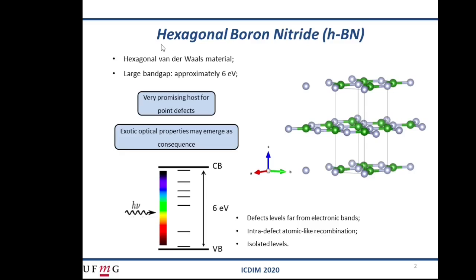Well, here we have a brief overview about some properties of hexagonal boron nitride. This material is formed stacking these hexagonal layers of boron and nitrogen, and this stack direction defines this z-axis direction. These layers are held together by van der Waals interactions, and this makes it possible to exfoliate the material layers. Its great band gap of approximately 6 electron volts makes it relatively easy to produce isolated defects in the material, which makes it possible to promote internal transitions between the energy levels of a defect. Possibly this is the most important optical feature of the hexagonal boron nitride involving point defects.